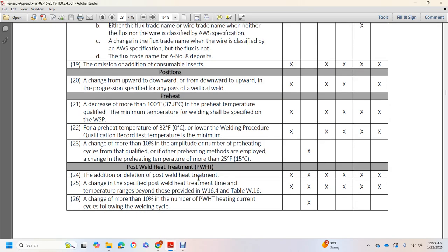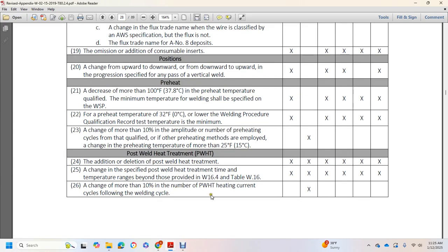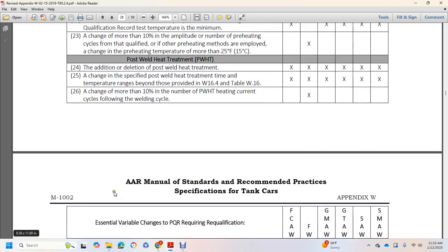Post-weld heat treatment: addition or deletion of post-weld heat treatment. Change 25: change of the specified post-weld heat treatment time. Temperature ranges beyond those provided in W16.4 and the table of W16. A change of more than 10% of the normal number of post-weld heat treatment heat cycles following the welding cycle.